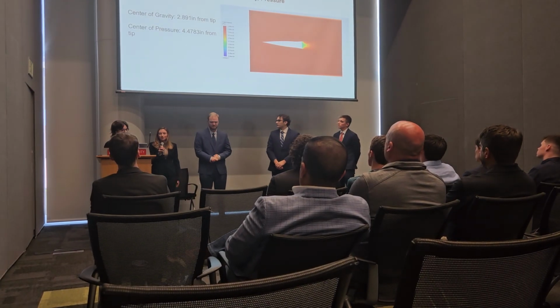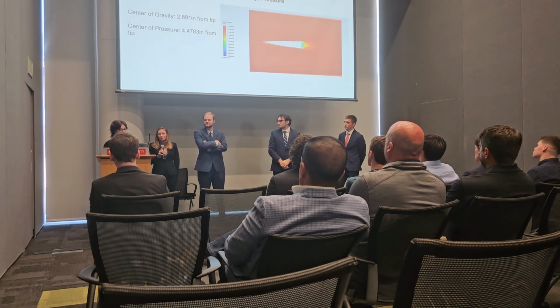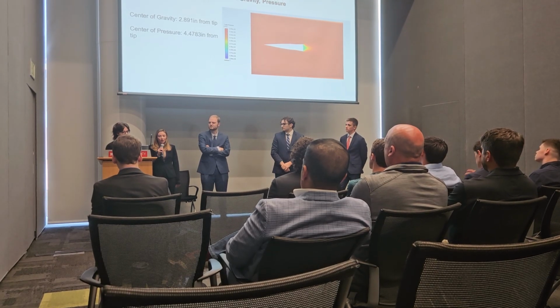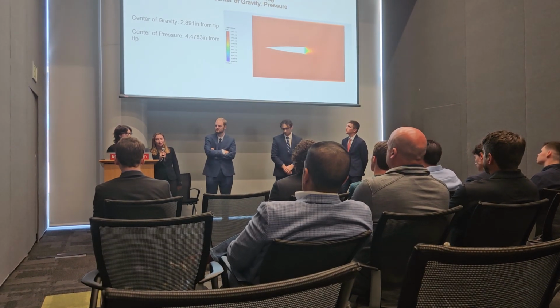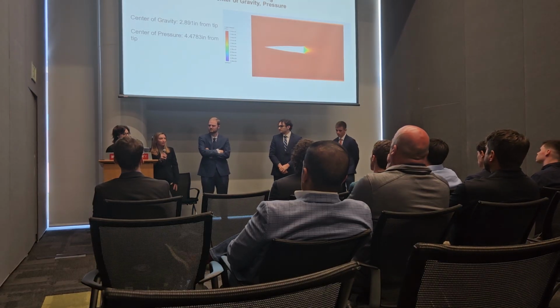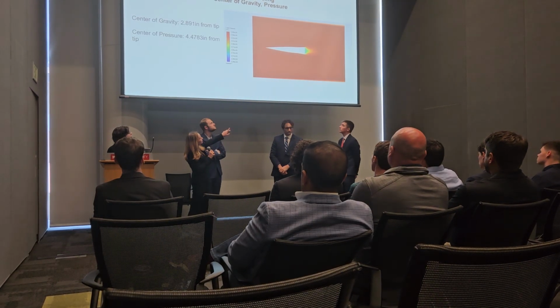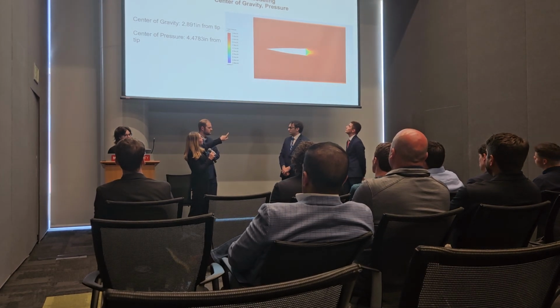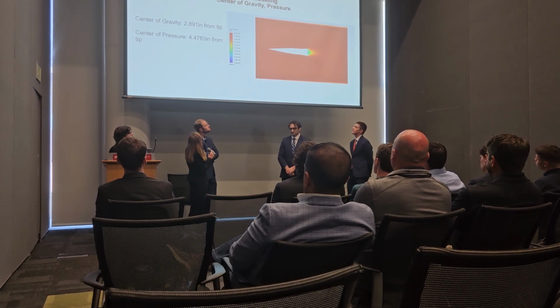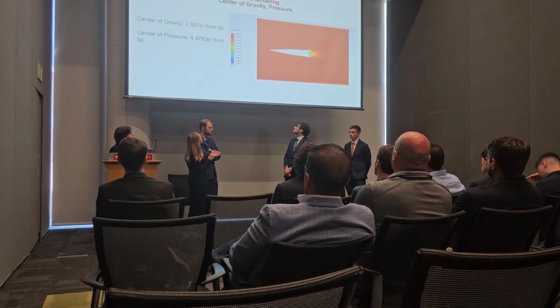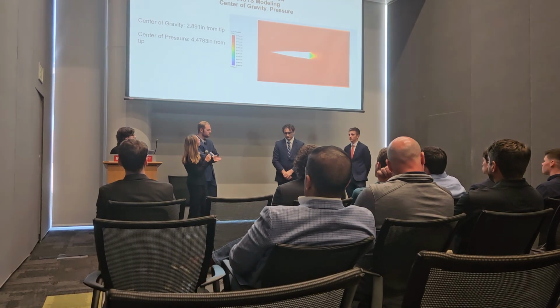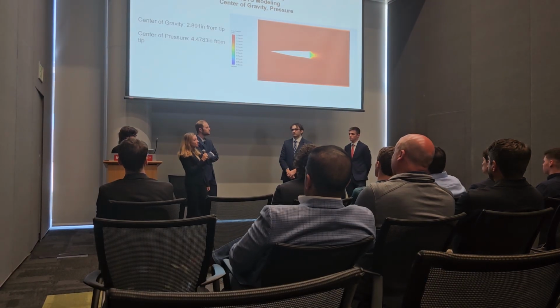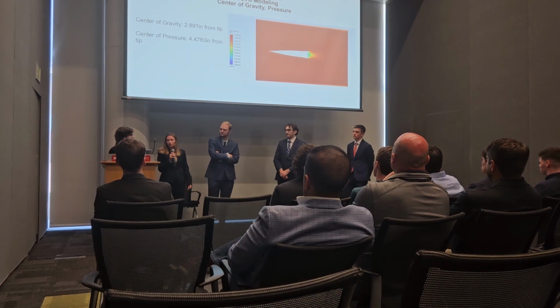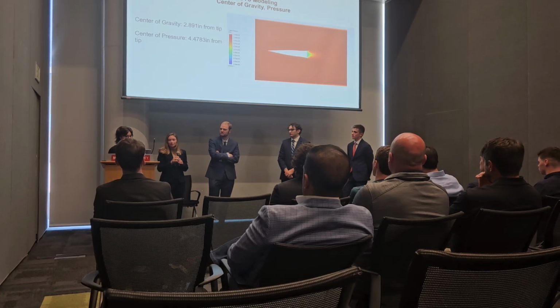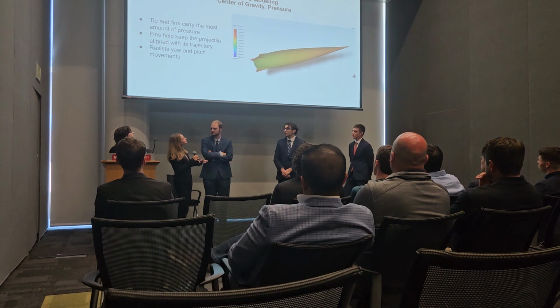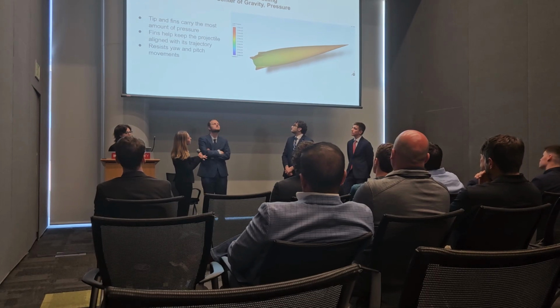Now we'll move on to just a quick overview of our modeling and analysis. So our center of gravity is about 2.89 inches from our tip, and in this graphic you can see this shows pressure, and behind our projectile there's a low pressure region. And so from this simulation we were able to find our center of pressure, which was 4.478 inches from the tip. And that shows us that the center of pressure is more towards the fins, which is what we'd like to see. So this is more of a simulation of the pressure on the body.